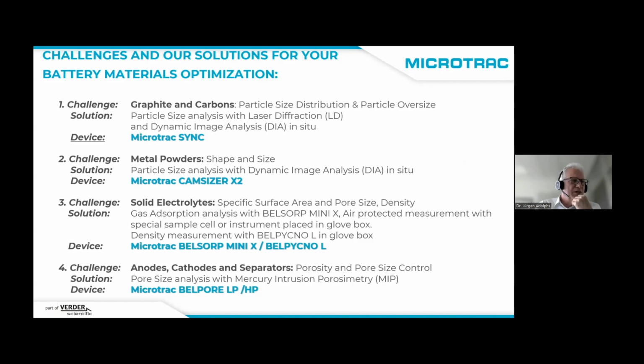Third challenge we faced were solid electrolytes. There was of interest the specific surface area and the pore size and density. So we did gas adsorption analysis with the BELSORP Mini X, air protected measurements with special sample cell, or you place the instrument in the glove box. Density measurements can be done with the BELPYCNO in the glove box, for example. And these were also the 2 devices we used.